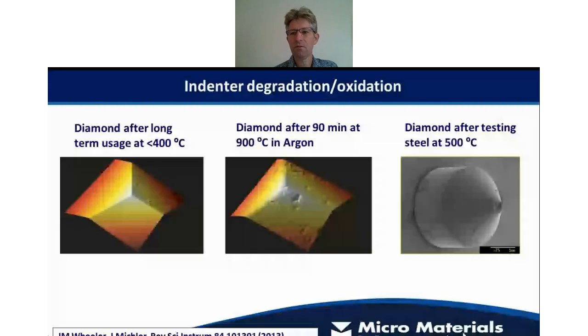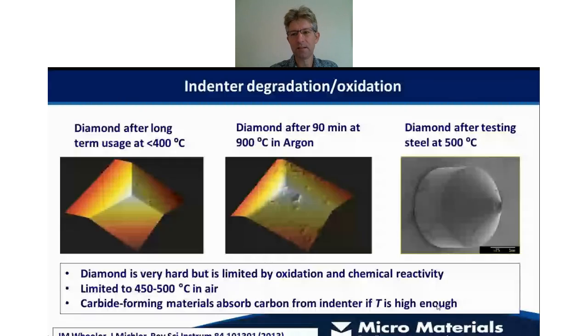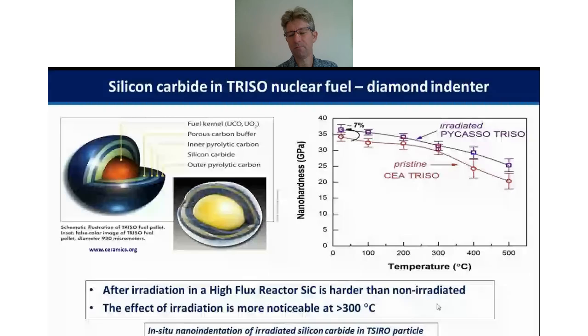So the other thing you need to worry about is that diamond itself isn't so effective at testing carbide formers such as steels, and this is again another image from Cambridge University, and what you can see there is that the top of the tip essentially has been burned away by contact with the steel sample. So we can say that essentially diamond is very good provided you can keep the temperature down, and that you really can't use it for testing carbide forming materials at high temperatures.